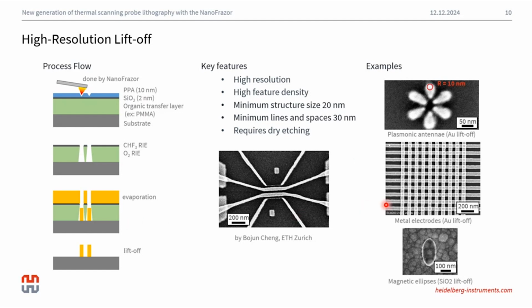So when it comes to the high resolution liftoff, this method allows for much higher feature densities, as you can see in these examples here. And when it comes to lines and spaces, we've achieved resolutions of 30 nanometer lines and spaces. And if we are talking about more isolated structures, then we can push this resolution even further to around 20 nanometers.